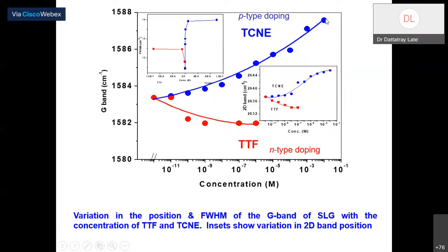You see, when you add TCNE, the G band shifts towards the higher wave number. And when I start adding TTF, the G band shifts towards the lower wave number. So this clearly indicates that when I add TCNE on the graphene sheet, the graphene becomes more P-type in conductivity. When I add TTF, the graphene becomes more N-type in nature. Again, this is because of the slight change in the band structure, and you can see as we increase the concentration of these molecules, there is a shift in the G band position.